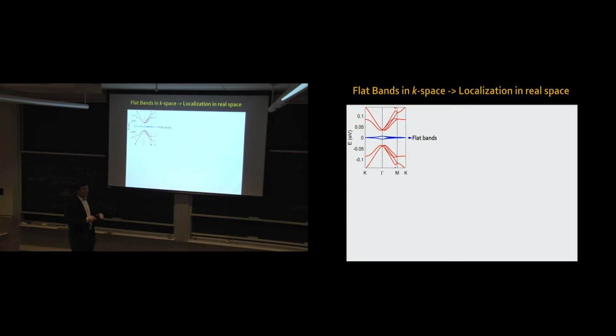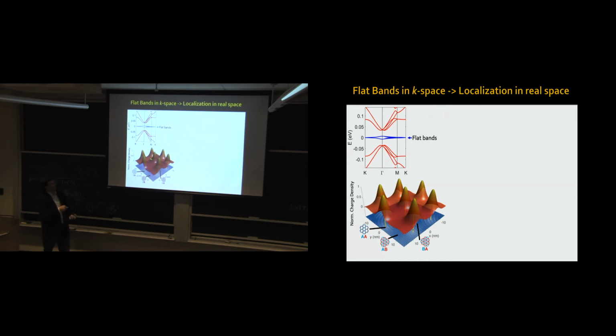So if you calculate what is the charge density in these flat bands, it happens to be highly localized in certain regions of this twisted graphene structure. In particular, you have very high density in regions which locally have this, what we call AA stacking - locally, all of the carbon atoms are on top of all of the other carbon atoms.